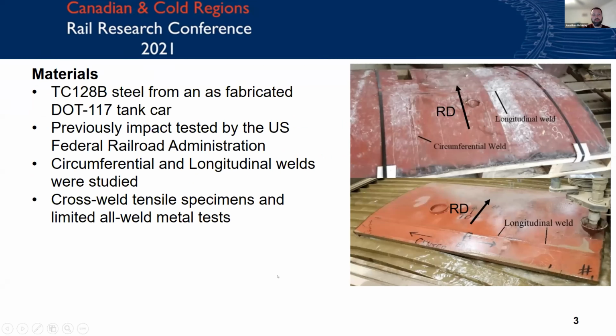So the material that we were testing is TC128B steel from an as-fabricated DOT-117 tank car that had been previously impact tested by the US Federal Railroad Administration. It was provided to us via Transport Canada from the FRA, and that was very helpful in doing these tests. We looked at some circumferential and longitudinal welds, as you can see in the pictures on the right. And we did many cross-weld tensile specimens and a few all-weld metal tests. There was a limit to the amount of testing that we could do on weld samples, which is why we used different types of samples.